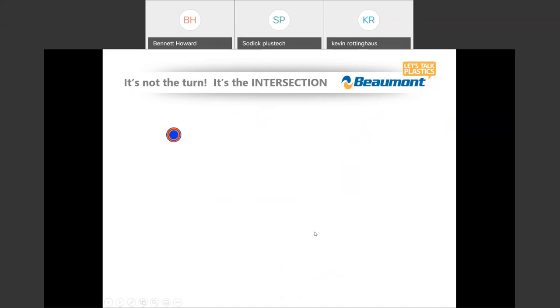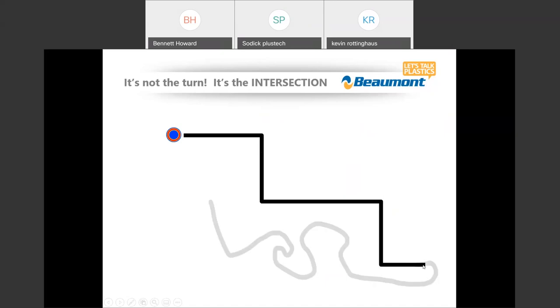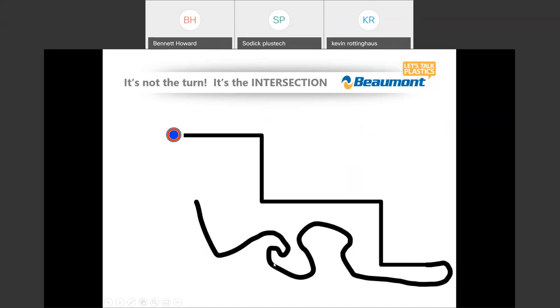It's not the turn. Sometimes when I talk to people about what we're seeing, the misconception is that by doing a turn somewhere we're creating an issue. We can turn runners all day long. We can take this annular ring and come up to, say, an elevation change, and that annular ring is going to stay just as it is coming through these turns. It's not going to split non-uniformly, so it maintains an annular ring. We can make more turns in the runner system, and it'll still be annular. We can get real crazy and make all kinds of turns and elevation changes, but if there is no intersection, if this laminate does not split, your shear profile still looks annular. So turning a runner or doing an elevation change does not change the shear profile.